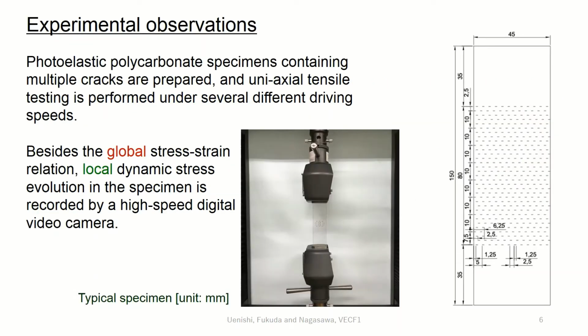Now let us briefly show you typical experimental results. As mentioned above, photoelastic polycarbonate specimens containing multiple cracks are prepared, and uniaxial tensile testing is performed under several different prescribed driving speeds or strain rates. Besides the global stress-strain relation, local dynamic stress evolution in the specimen is recorded by a high-speed digital video camera. The right figure illustrates an archetypal specimen used and elongated by the tensile testing machine.